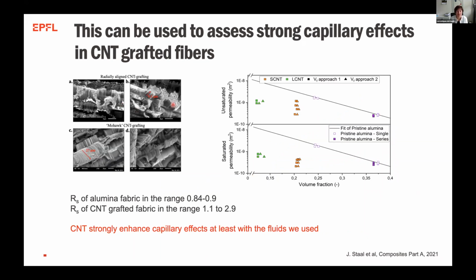We can also use this, and that was recently done by Hirun in the paper we just published, this time using fibers that are grafted with carbon nanotubes. So all these fibers are grafted with a forest of carbon nanotubes. We managed to measure the permeability of these, and of course compared it to the pristine alumina, saturated and unsaturated.